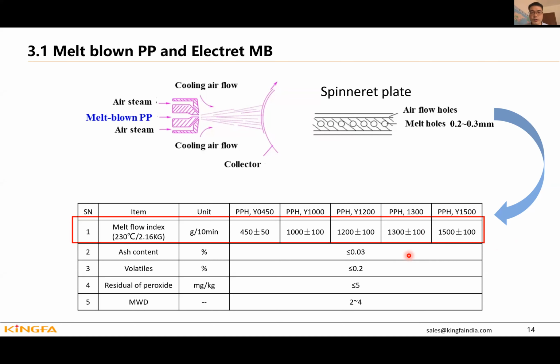Besides that, we need to control other properties such as ash content. If they have some ash content in meltblown PP, it's very easy to block these small holes. If the hole is blocked, we need to stop the production and clean the spinneret plate and clean all the holes. So this is very hard work. So when we choose the meltblown PP, we need to follow this requirement. Then we can get continuous production.